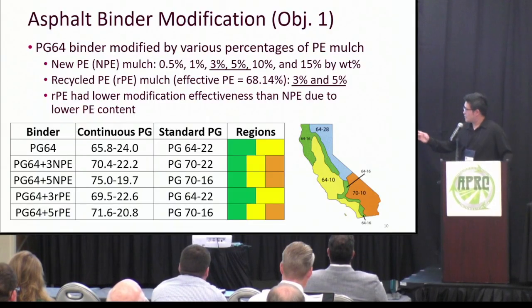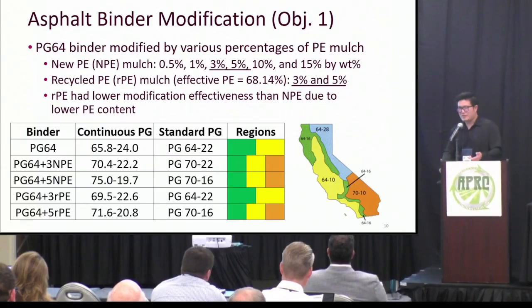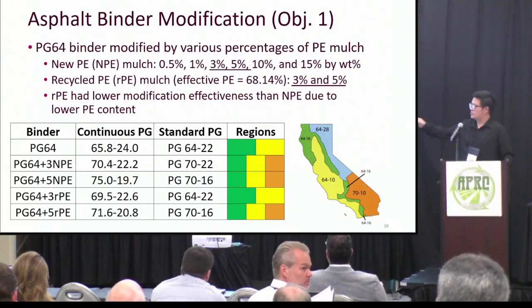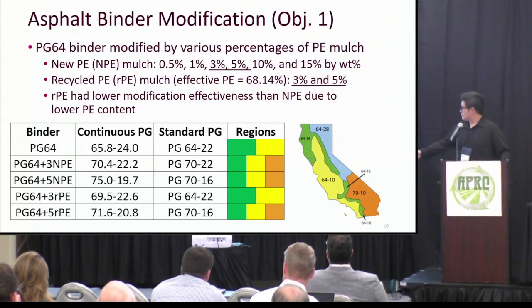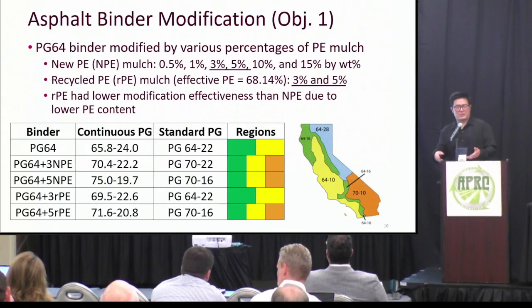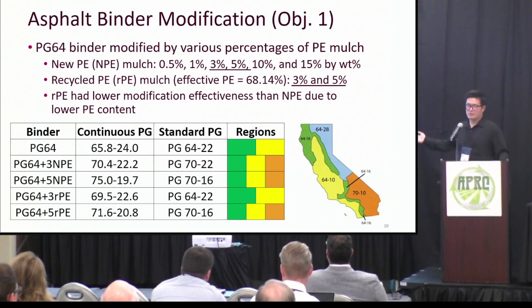And the results show, if you see this table, that if we use new PE mulch to modify the binder, it can extend the binder use in California, for example, to the hot area. So it reached PG 70. And similarly, when we use recycled PE mulch to modify asphalt, it also can extend the asphalt use in California, for example, to the hot area.